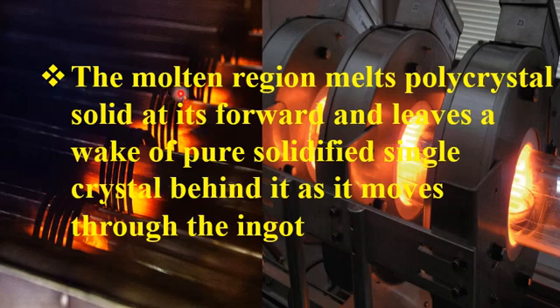So in this zone refining process, a narrow region of the polycrystalline material is melted and moved along the forward direction. After moving, the molten region of the polycrystalline material solidifies along the forward direction. So it leaves the pure solidified single crystal behind as it moves along the forward direction. So let's explain it in a simple way.